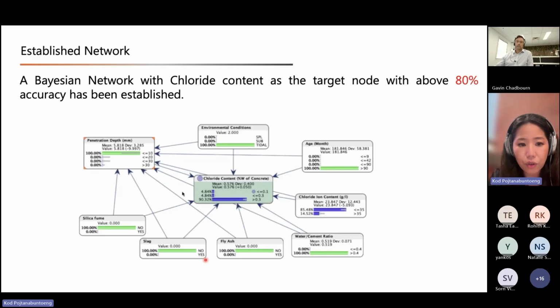We don't have any silica fume. We don't have any slag. We don't have any fly ash. In this case, there is a 90% likelihood that we will have a chloride content at that particular location, at the concrete depth of 10 mil, of more than 0.3 weight% of concrete. So this is how we could use the currently established model.